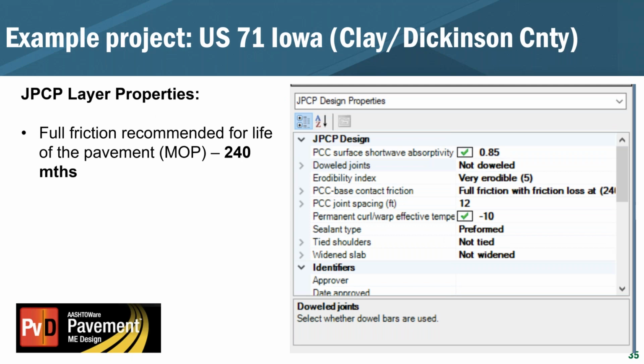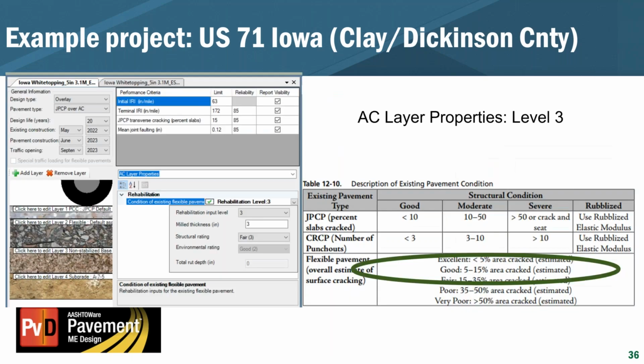So it was a 20-year design. So for a full 240 months, full friction was assumed based on what's suggested in the manual of practice. And then for the asphalt layer properties, again, this is where we want to account for that reduction in stiffness in the asphalt layer, which is automatically done based on the amount of fatigue cracking.